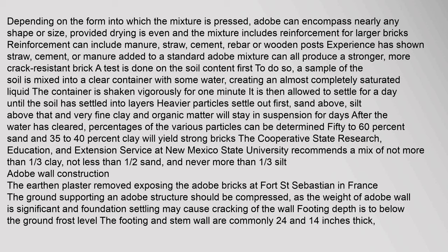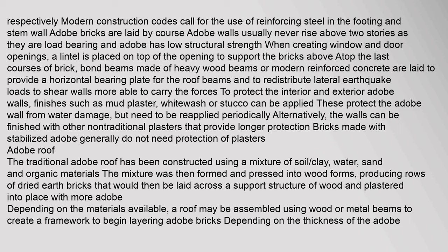The ground supporting an adobe structure should be compressed, as the weight of an adobe wall is significant and foundation settling may cause cracking of the wall. Footing depth should be below the ground frost level. The footing and stem wall are commonly 24 and 14 inches thick respectively. Modern construction codes call for the use of reinforcing steel in the footing and stem wall. Adobe bricks are laid by course; adobe walls usually never rise above two stories as they are load-bearing and adobe has low structural strength. When creating window and door openings, a lintel is placed on top of the opening to support the bricks above. Atop the last courses of brick, bond beams made of heavy wood beams or modern reinforced concrete are laid to provide a horizontal bearing plate for the roof beams and to redistribute lateral earthquake loads to shear walls. To protect the interior and exterior adobe walls, finishes such as mud plaster, whitewash, or stucco can be applied. These protect the adobe wall from water damage but need to be reapplied periodically. Alternatively, the walls can be finished with other non-traditional plasters that provide longer protection. Bricks made with stabilized adobe generally do not need protection of plasters.